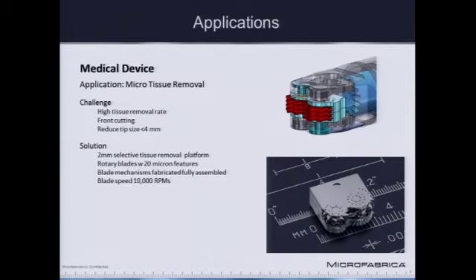What are the challenges? We want to make this remove material at a very high rate. It's going to be front cutting, and if you're in the industry, most of these devices that remove material are side cutting. Rarely is there a device that actually cuts from the front. And then also reducing this tip size to 2 millimeters and potentially smaller. One of the applications, tumor resection in the neurovascular area in your brain, being able to selectively remove material without damaging material on the side.